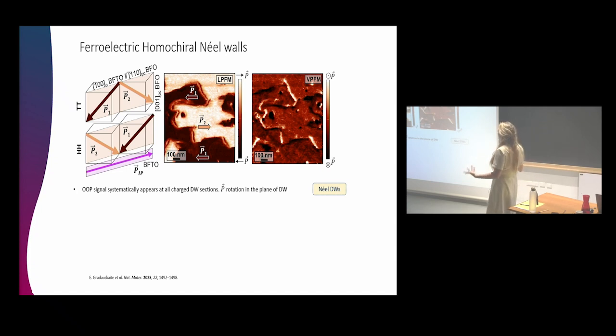So in this case, because of the geometry, we know that these are going to be ferroelectric Néel domain walls. And what's interesting is that there's always the same deterministic sense of rotation. So for every head-to-head domain wall, let's say this one here, we know that it's going to be down polarized, and for every tail-to-tail domain wall, like here, it will be up polarized. So there's some net chirality in the film, some net preference of how the polarization is rotating in these walls.